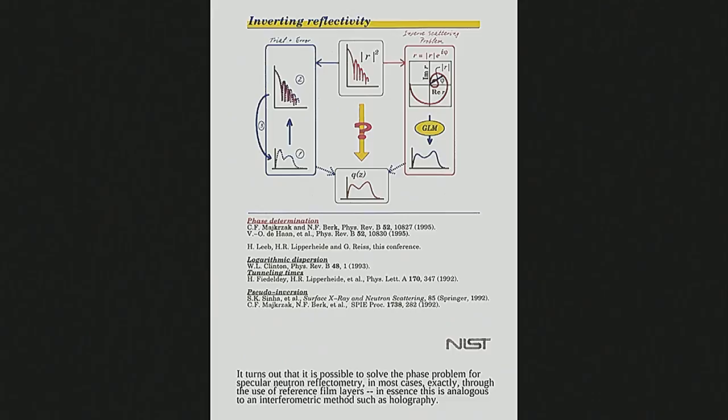So we're actually reduced to a trial and error system, which still works, where you fit the data by taking different models and seeing how well they fit the data. And the right solution is in there. The trouble is there are other ambiguous solutions along with it, and you have to somehow separate them. If you were able to measure the reflection amplitude with the phase, then it turns out, even though this is not the exact Fourier transform, even though we're solving the Schrodinger equation in the so-called dynamical or strong scattering regime, you can still find a mathematical way of retrieving unambiguously and exactly that reflection profile without the error.